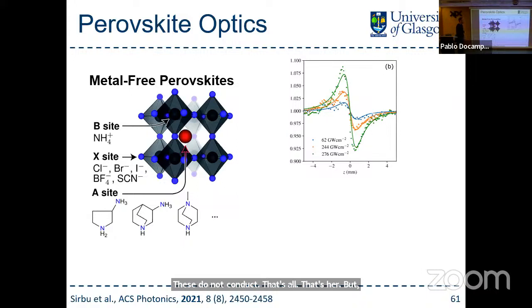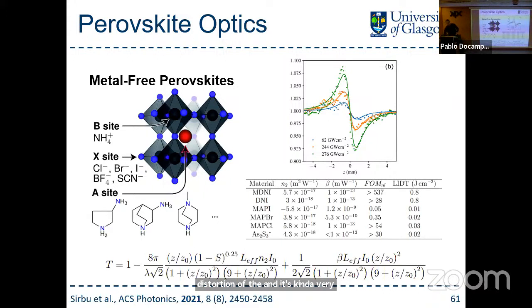But they've got a very strong nonlinear refractive index. Okay, so this is a Z scan. Basically, you illuminate your sample and you move it in and out of focus. So you can start up nonlinear processes in your device. You can look at the nonlinear absorption, and that gives you the nonlinear refractive index. So this is the third order nonlinear refractive index. It's just due to the distortion of the lattice. And it's got a very strong nonlinear refractive index. I'm not going to get into the equation for how you fit it, but the main thing is that these materials have a very large laser damage threshold and a strong third order nonlinear refractive index, which actually makes them really interesting for optics applications.